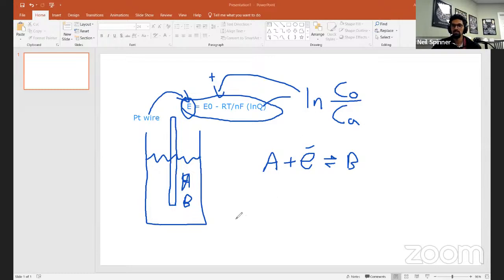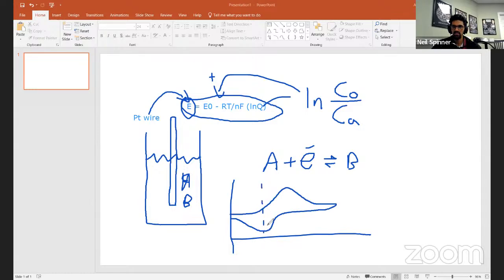And this is related to when you're doing a cyclic voltammetry experiment and you want to know why there is a difference between these peak potentials, right? That difference typically is around 59 millivolts, or 60 or 57. 59 is, I think, the number. Mathematically, it works out something like that. Because I think Matt was asking about this difference, and it's 100% just due to the